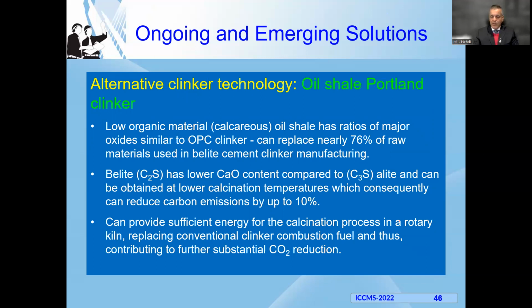There are low organic materials, we call them calcareous oil shales, that have ratios of oxide compositions that are similar to ordinary Portland cement, and those can replace maybe 3/4 of the raw materials when we manufacture belite cements. Belite cements. What are belite cements? Well, the cement components, and we will come to this a bit later maybe. Cement clinker has C2S, which is belite, C3S, which is alite, and then C3A, C4AF. So high belite cements, essentially, contain a larger quantity of C2S. They would be rich in C2S. And C2S, unlike C3S, can be produced at lower calcination temperature and would probably lead to less CO2 emissions.